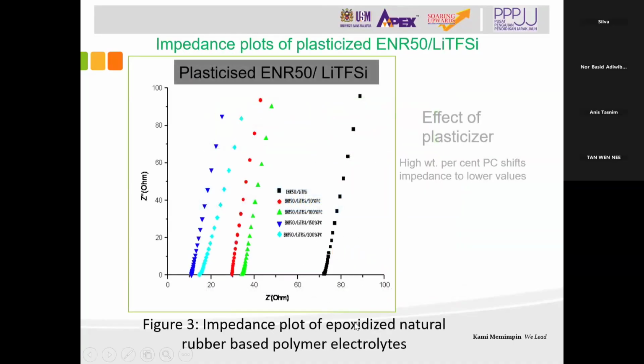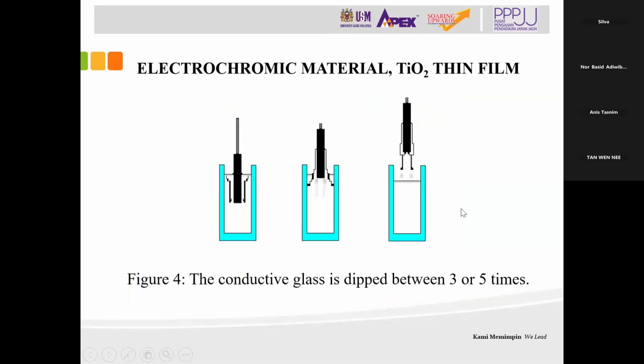After that we do some impedance plots. Here we use PC as the plasticizer. With a high weight percent of PC plasticizer, we shift the impedance to a lower value. Then we want to make some electrochromic windows. So we have to make some electrochromic materials, which is the TiO2 thin film.